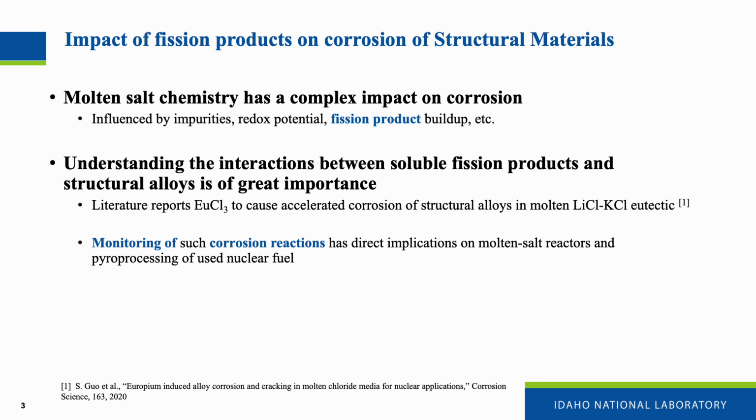So today I will talk about one particular fission product, europium chloride. It is known to accelerate corrosion of structural materials in molten salt, specifically molten LiCl-KCl eutectic salt. LiCl-KCl eutectic salt is used as the electrochemical media for pyroprocessing applications, which is reprocessing of used nuclear fuels. So that's why I'm considering this system for today's talk. And in general, monitoring of such corrosion reactions has direct implications on molten salt reactor design.